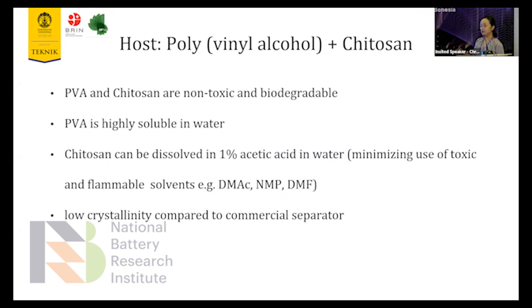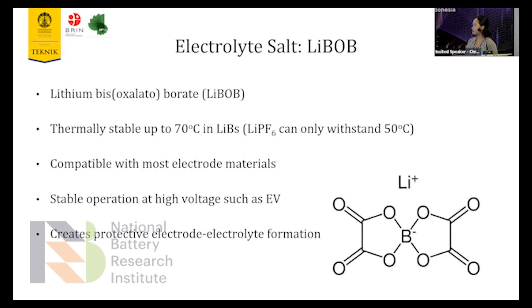And it will be minimizing use of toxic and flammable solvent that is currently used, such as dimethyl acetamide, DMAC, or NMP, or DMF. And lastly, it has low crystallinity compared to commercial separator. The electrolyte salt, we use lithium bis(oxalato)borate, which is thermally stable up to 70 degrees C. It is compatible with most electrode materials, and it is stable at high voltage.